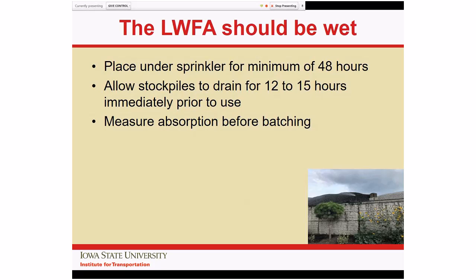We could back calculate how much water was coming in with the aggregate on the surface, and so we could still control the water cement ratio of the final mixture. But it is a good idea for the aggregate to be thoroughly wetted. Now, we're not talking about huge quantities. If you look at a typical bridge deck like the one we built, I believe we're only looking at a couple of truckloads. So it is a pain, but it is eminently manageable. Now, when we come to pavements, it's a little bit harder because the quantities go up pretty quickly.